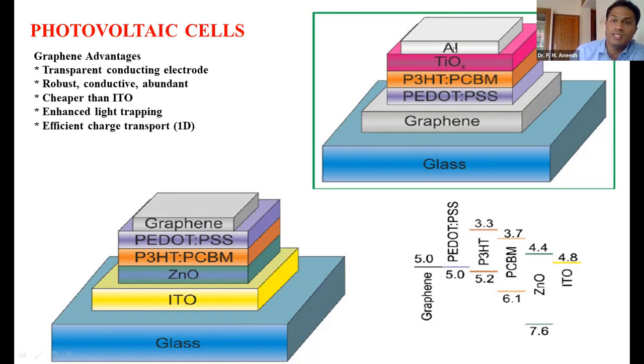Here the aluminium is opaque, so light cannot enter the active material from that side. The light can enter through the glass, graphene, and PEDOT:PSS, which is also a transparent material. Finally the light reaches the P3HT:PCBM, where it splits into electrons and holes. Electrons go in one direction and holes in the other, so they are separated, and that acts as the current. The solar cell is nothing but a conversion of light energy into carriers or current. Since graphene is transparent, the light can enter the active region through this transparent graphene.